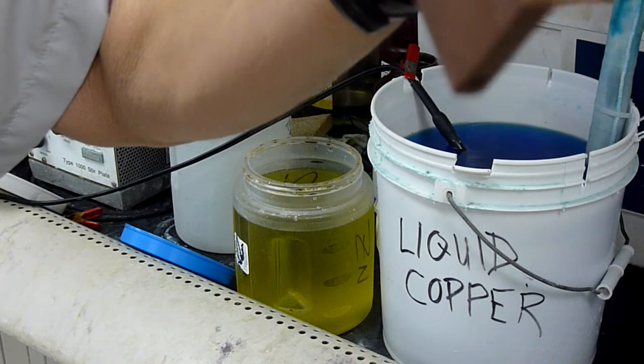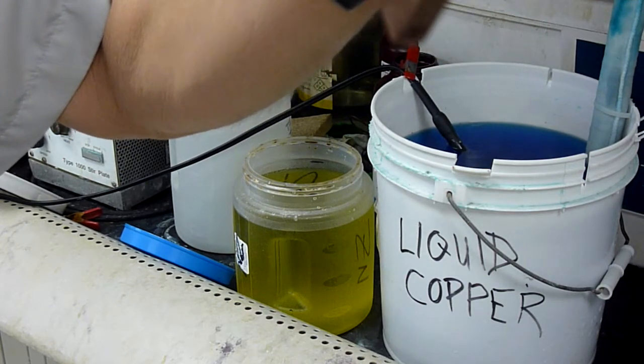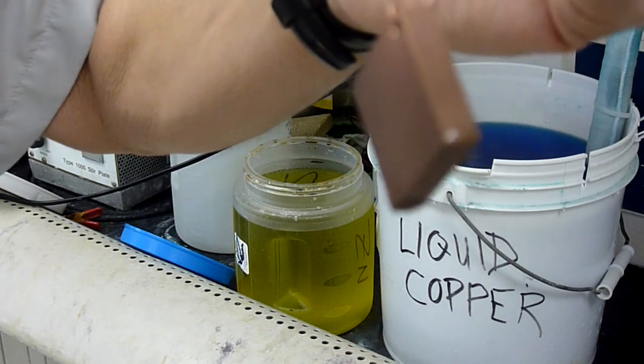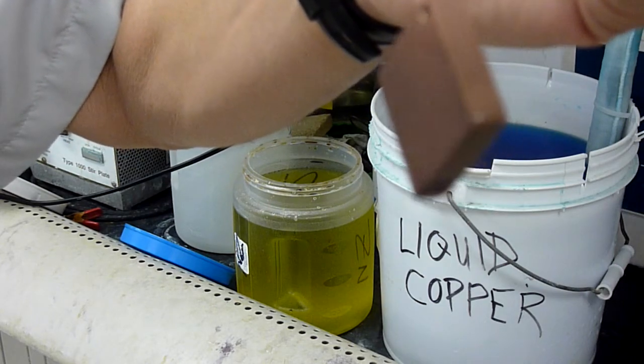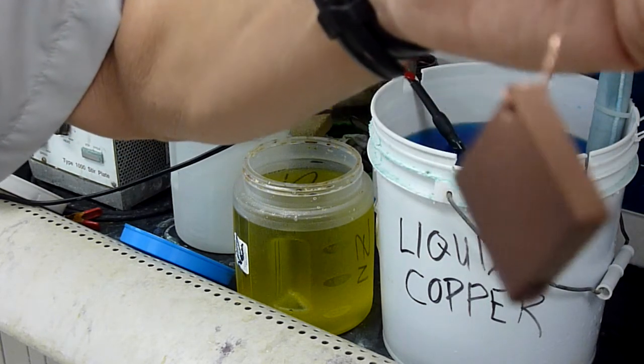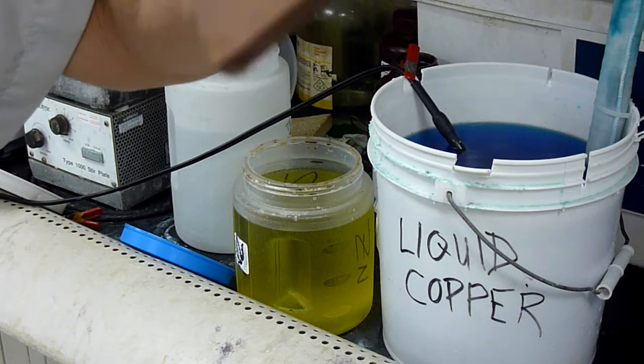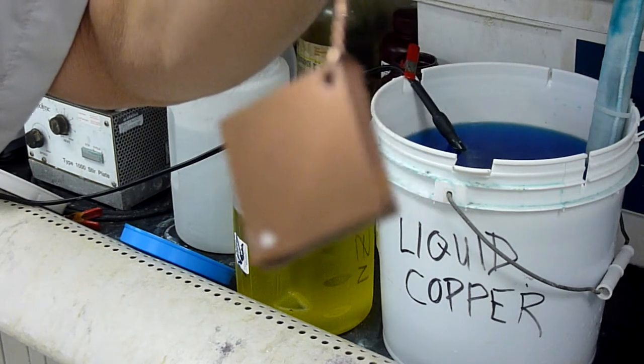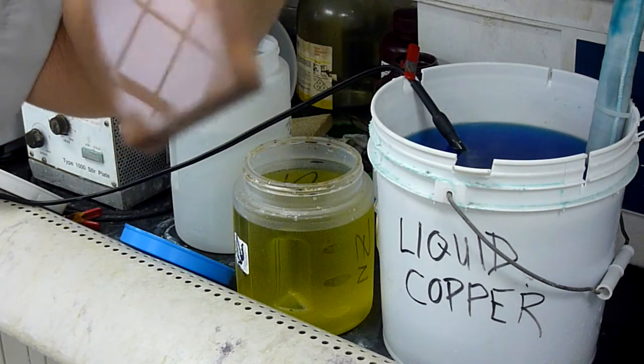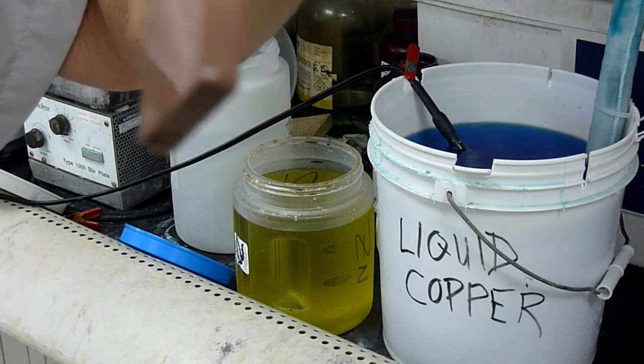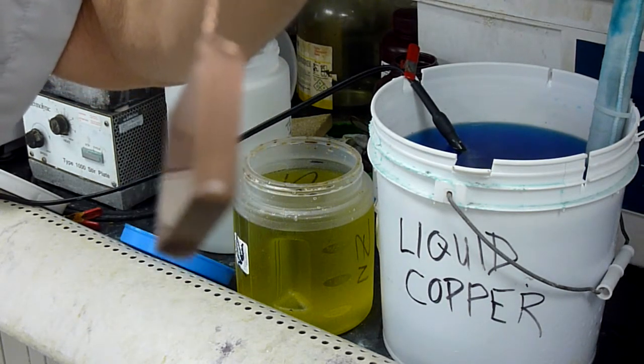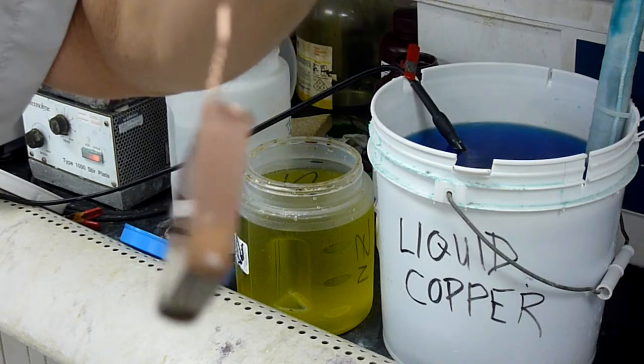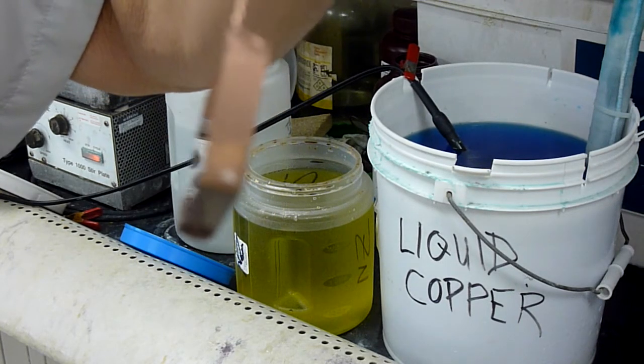You wouldn't want this as a finished copper plate. It doesn't look that pretty. But if this is just a base coat, a barrier layer between the zinc-ate and gold plating, I'm pretty sure I could go into the gold tank now and get a decent result on this part. So that's it. That's a quick look at how we do zinc-ate to prepare for copper plating on aluminum. And zinc-ate plating is essential anytime you want to plate anything onto aluminum.